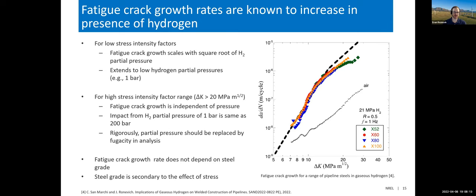What we have seen is that for low stress intensity factors or low loads on the pipe, fatigue crack growth generally scales with the square root of hydrogen partial pressure. And this happens even at low hydrogen partial pressures, as low as 1 bar. At higher stress intensity factors, however, we see that fatigue crack growth rate is actually independent of hydrogen partial pressure. And so for pipelines operating under high stress environments, the impact of 1 bar of hydrogen partial pressure is approximately the same as 200 bar. And I should note that rigorously we should really be considering fugacity instead of partial pressure, but it's a bit of a side note.